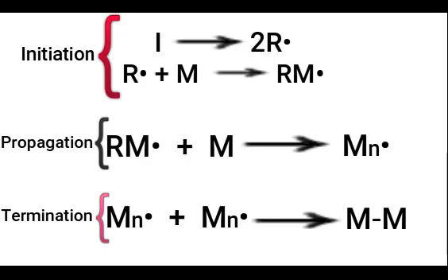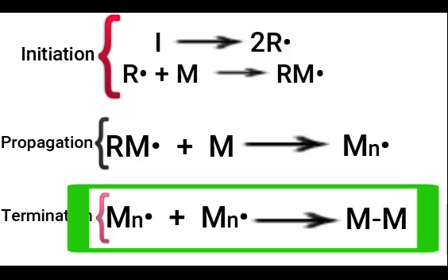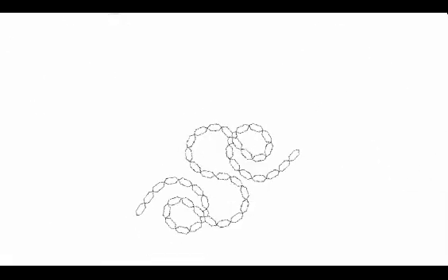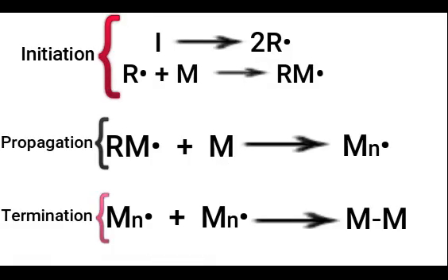This happens because the polymer chains also get longer as the reaction proceeds. This increases the viscosity of the substance. This increase in viscosity has important implications for the termination reaction, where two active chain ends couple together. This termination reaction is diffusion controlled, meaning that the rate of the reaction depends upon the ability for the two active chain ends to find each other, rather than the energy barrier required for them to react. This is due to a low activation energy.